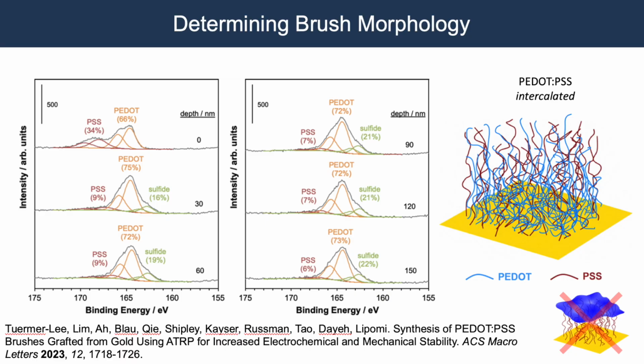What's important from these data, or what's important using this technique, is that the conductive material actually penetrates all the way down to the metal surface, and that means that you're retaining this three-dimensional structure of electronic and ionic conductivity on the metal, and you don't just end up with this like day-old cold pizza cheese that you could peel right off of a surface where the conductive part is just lying on top. You really need it to be interpenetrated into the surface in order to work well.